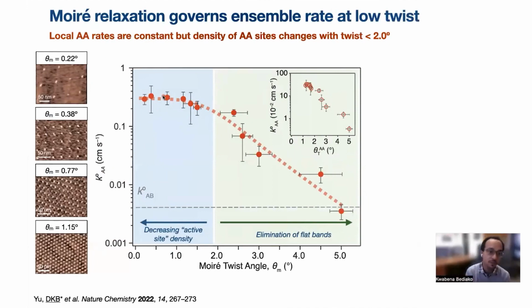And all you're changing as you go from this point to this to that, as you change the Moiré angle and decrease it below about 1.5 or 1.6 degrees, is you're simply spacing out these reactive hotspots from each other. As you decrease the angle, you're spacing these out. And so in that sense, these AA sites are a type of defect, right? These AA sites are indeed a topological defect that is introducing a large localized density of states, and we are able to modulate the defect density very precisely. We have a very controllable defect, which is controlled by the Moiré angle.